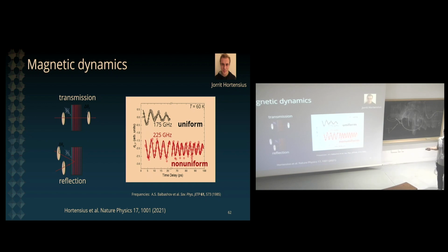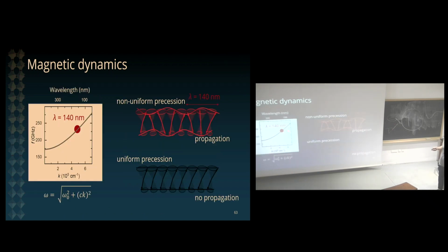So what's going on? Why do we see two completely different frequencies happening in our sample? Well, in this detection scheme, we are sensitive to a uniform spin precession mode only, while here we are sensitive to a specific component of a propagating wave packet that satisfies the Bragg condition, which in this case is this 225 gigahertz mode. So this corresponds to the spin system oscillating with a wavelength of 140 nanometers, according to the spin dispersion of this system.